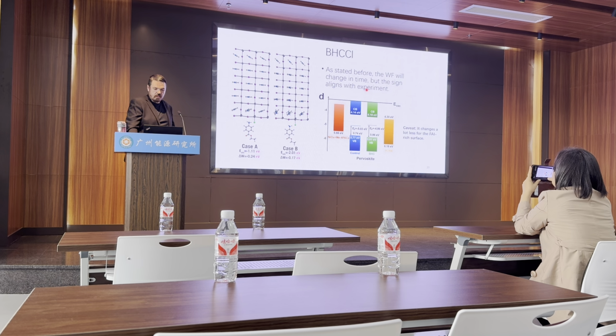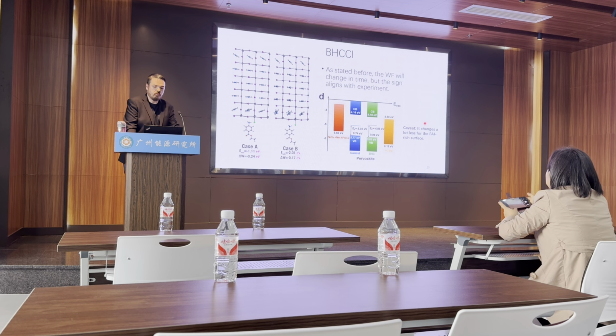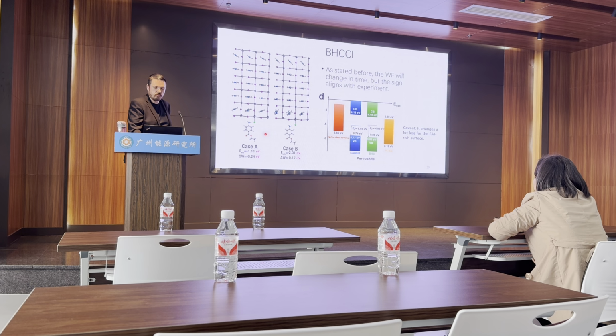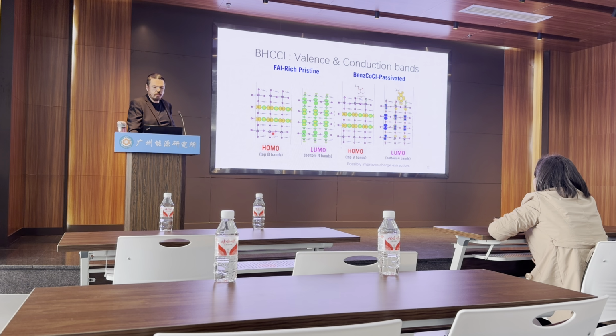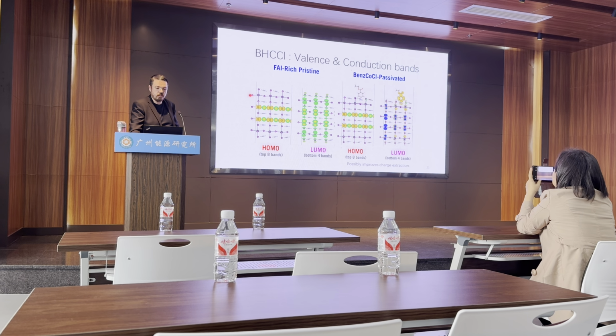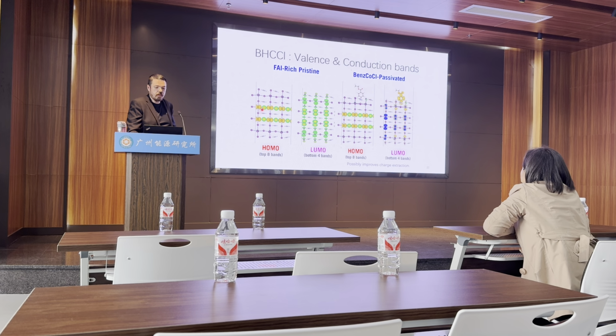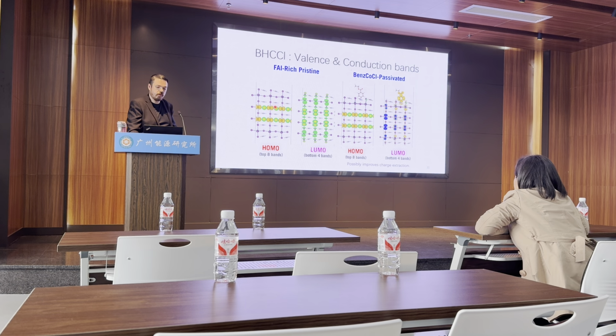But the caveat is that these changes will be much less for the formamidinium iodine rich surface. So we don't expect such big changes for the other surface. And the cool thing here is we can look at the HOMO and LUMO and just see what passivation does. In this case, for the unpassivated but pristine surface, the HOMO, the valence band maximum, localizes inside the bulk, which is interesting. And the conduction band minimum is delocalized. For the passivated case, the valence band is the same, but the conduction band shows that the electron will somewhat localize at the passivator, so that's probably good for charge extraction. So this needs to be investigated more, but this is a very promising result actually.